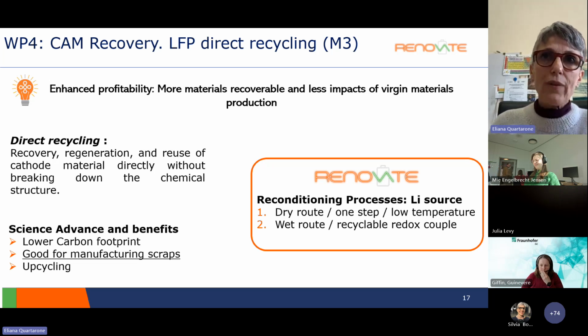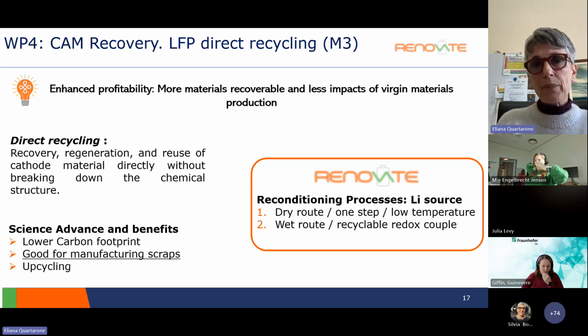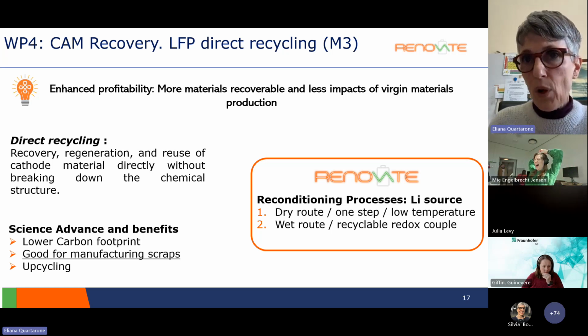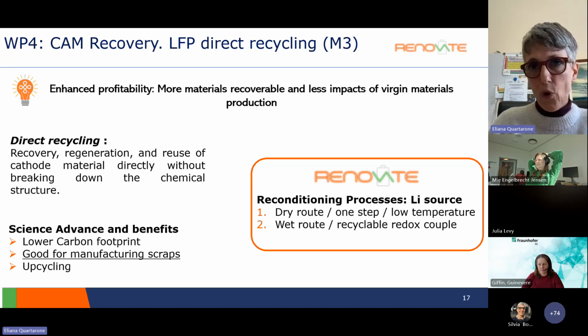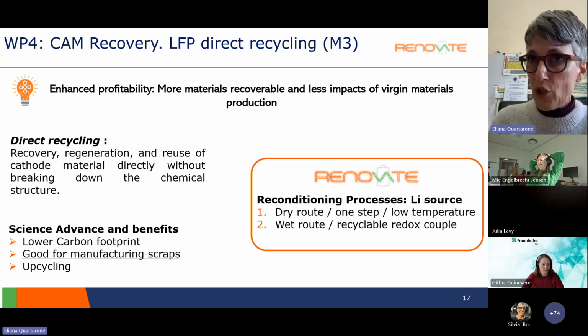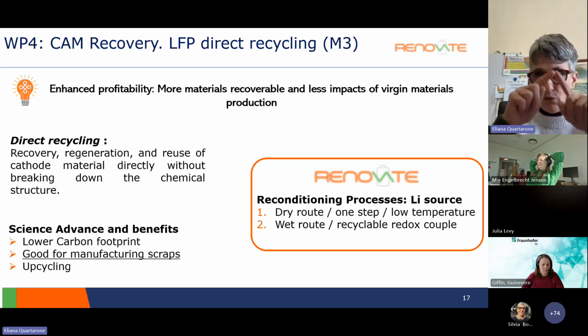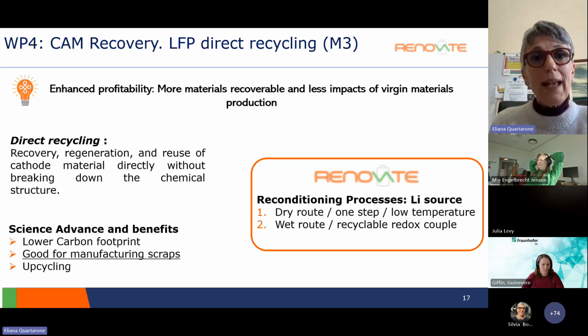And this, in case of LFP, is really important because, of course, as you know, there is a physiological lithium loss from the cathode because we are forming a solid electrolyte interface, and also the microstructure and morphology can change. Just think of the carbon coating, for example. So we are developing here two types of reconditioning process.